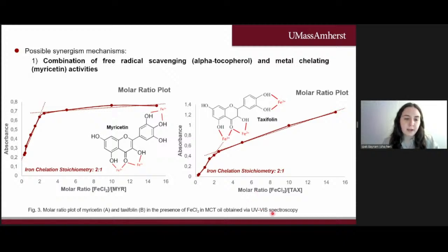The UV-Vis spectroscopy result has shown that both antioxidants can chelate the ferrous iron in oil with the same stoichiometry. The logic here is that we've already shown that myricetin and tocopherol are synergistic. So if the mechanism is due to the metal chelating ability of the flavonoid, we would expect taxifolin to be synergistic with tocopherol as well.